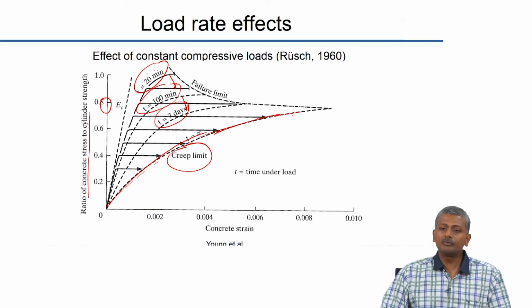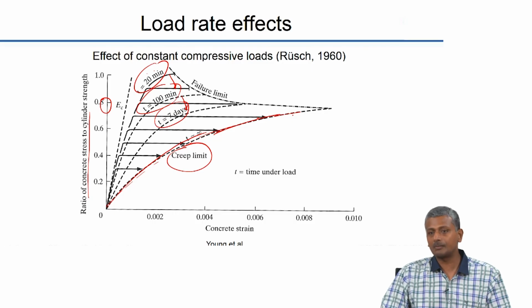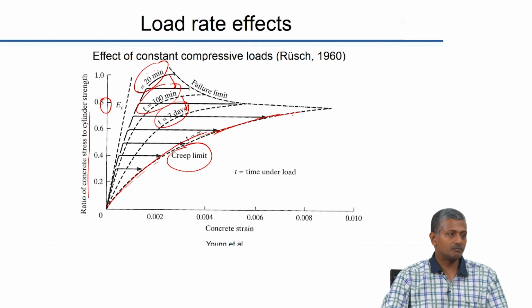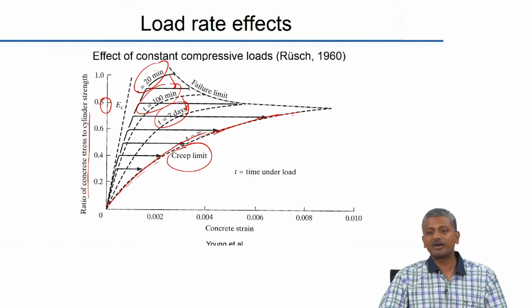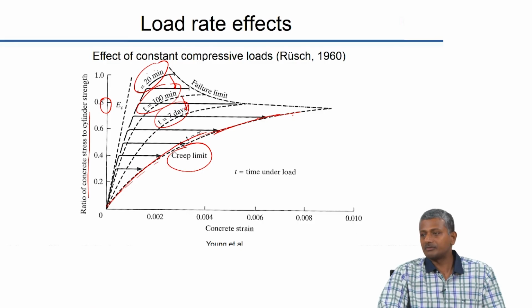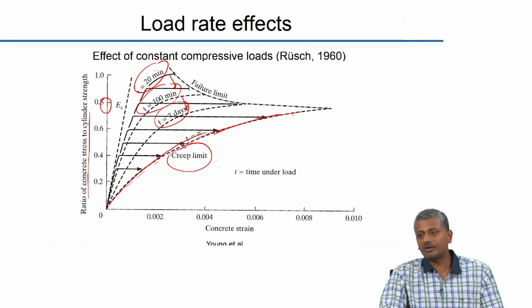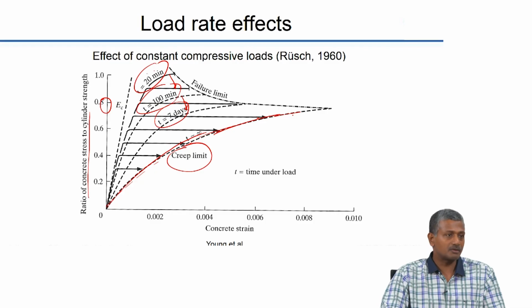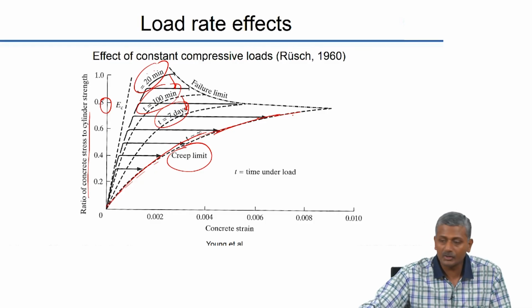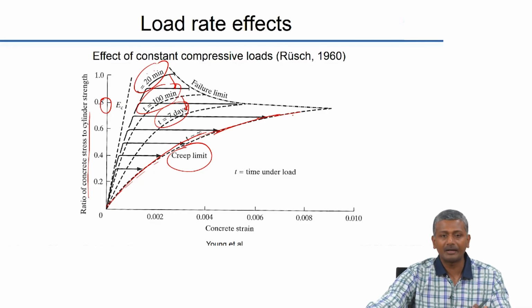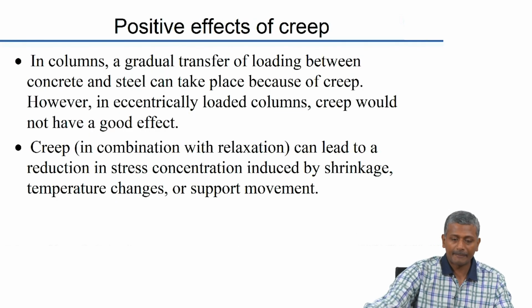Now, all the more so when you test polymers, this is even greater of a factor. Not just the temperature, but also the rate of loading has to be very clearly specified when you are testing polymers. So, there the effect can be even more drastic than this. With concrete you see some effect, but if your test varies between 5 minutes and 10 minutes, it is not going to make much of a difference. In the case of a polymer, even 5 to 10 minute difference can be quite significant because of the effects of creep that are coming in at slower loading rates.